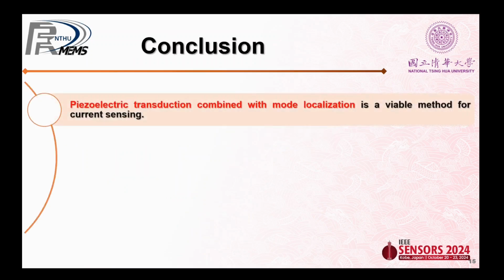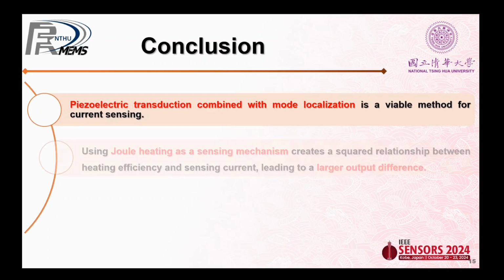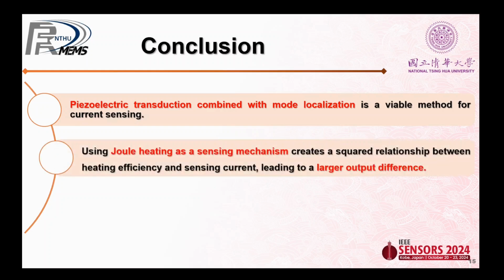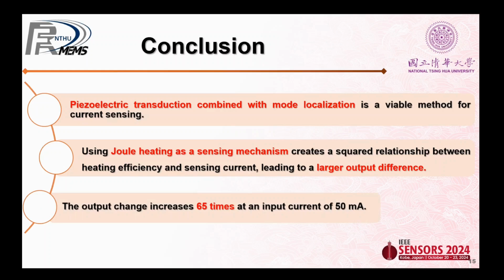And the conclusion part. In this research, we successfully combined piezoelectric transduction with mode localization effect for current sensing. And next, one of the benefits of using Joule heating as the sensing mechanism is that it provides a squared relationship between the sensing current and the output index, resulting in a greater sensitivity compared to linear sensors. And finally, we verify the mode localization phenomenon, demonstrating that using amplitude ratio results in a 65 times enhancement of the calibrated index.